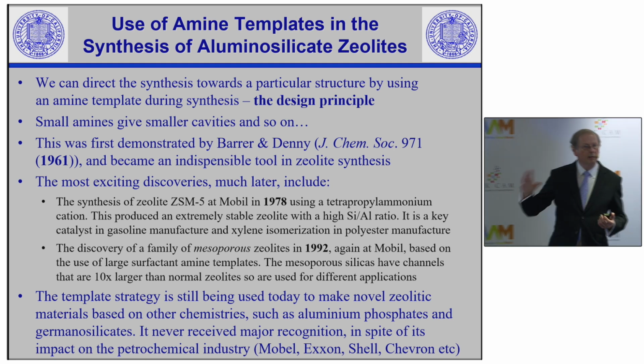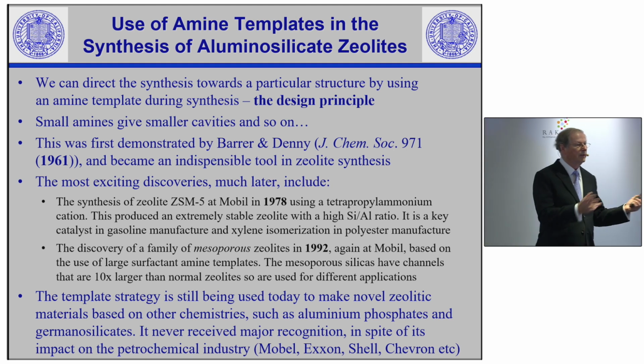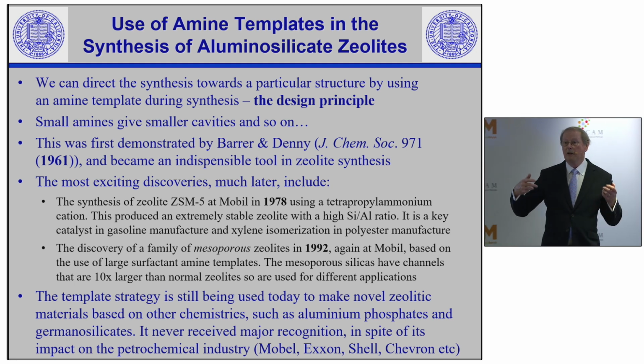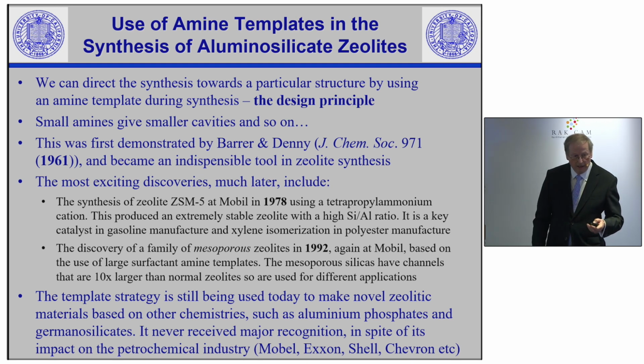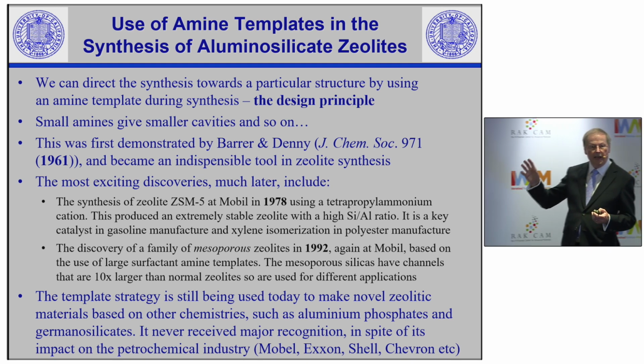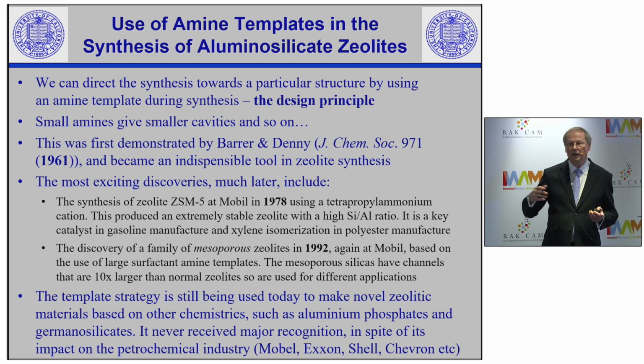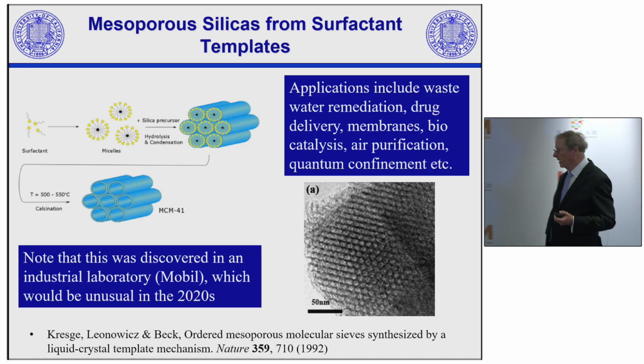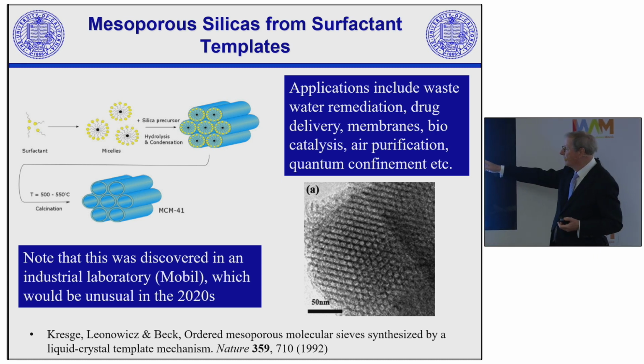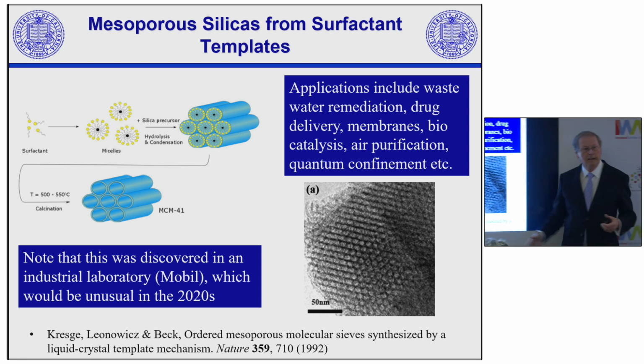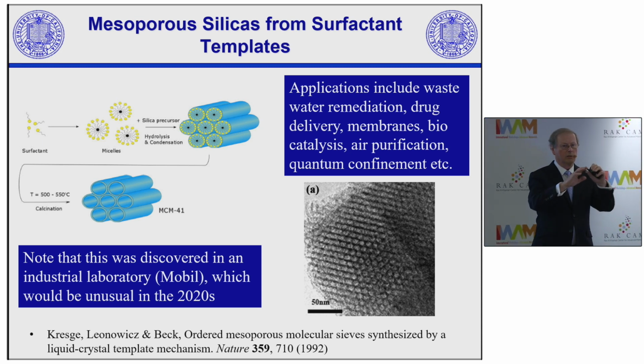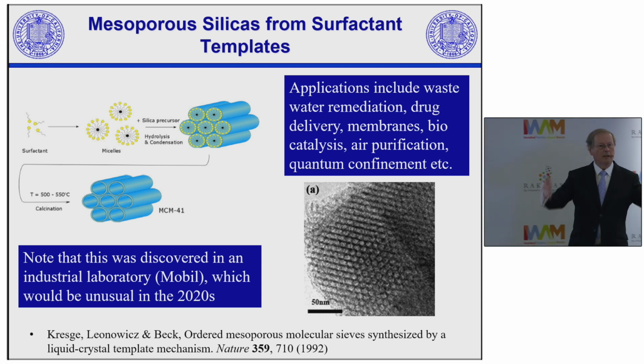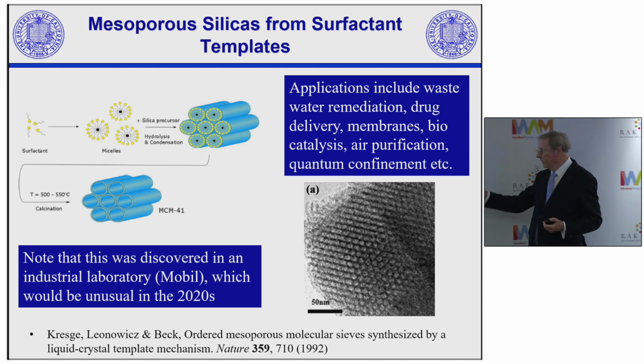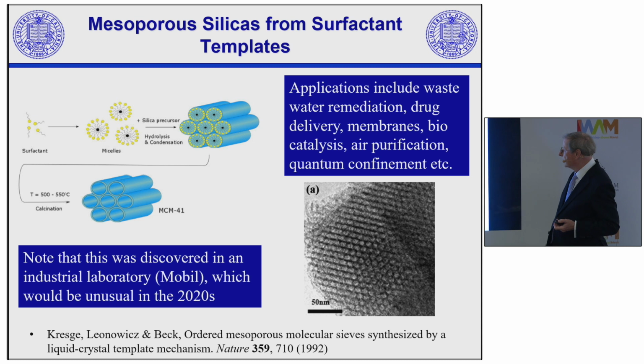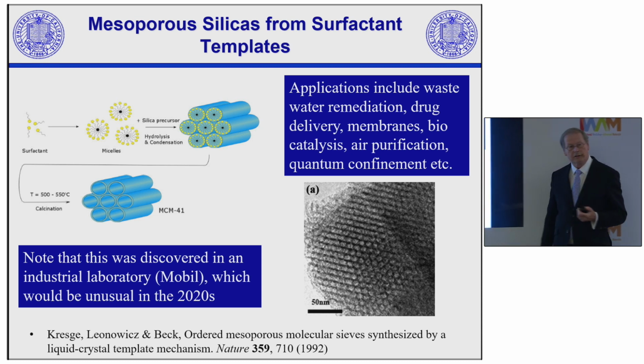And so this strategy is still being used today. When we were doing the article, I found very recent, interesting articles where people have used this principle in a variety of different chemistries, not just aluminosilicates, but with aluminum phosphates and germanosilicates and so on. So this is the mesoporous silica, where you use these large surfactant cations, and they self-assemble into tubes, and then the silica condenses around them. And then you can burn the surfactants out afterwards, and you get these porous structures.